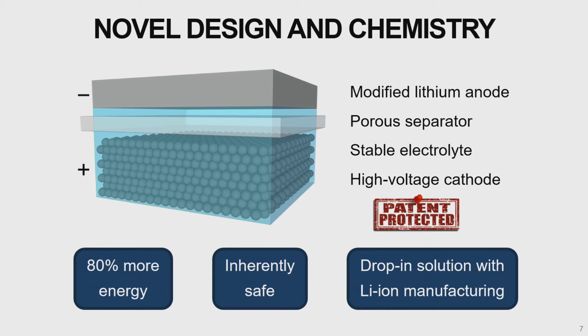And then on the cathode side, which is still the heaviest component of the battery, because of the chemical stability of our electrolyte, we're able to use much more aggressive cathode materials that perhaps may not be entirely stable in organic electrolytes, but we can actually cycle these materials at high voltage and get about 30% more energy on the cathode side compared to the best lithium ion in the world, without any of the safety or reliability challenges that they run into. So improvements throughout the system let us get to that roughly 80 to 100% improvement on specific energy, and with inherent safety, because of the non-flammable electrolyte that we're using.